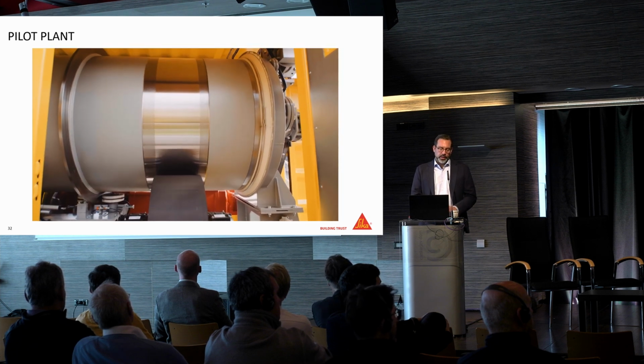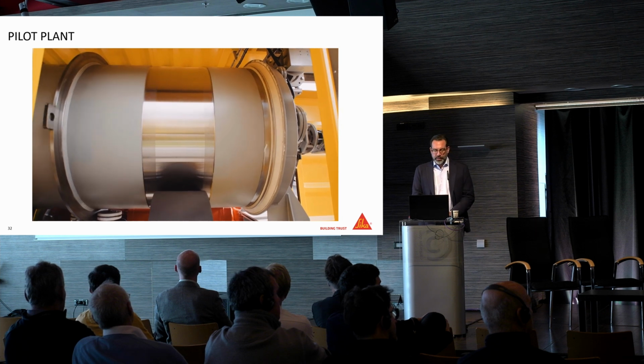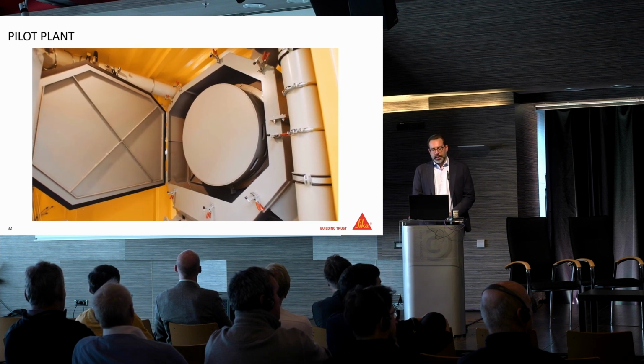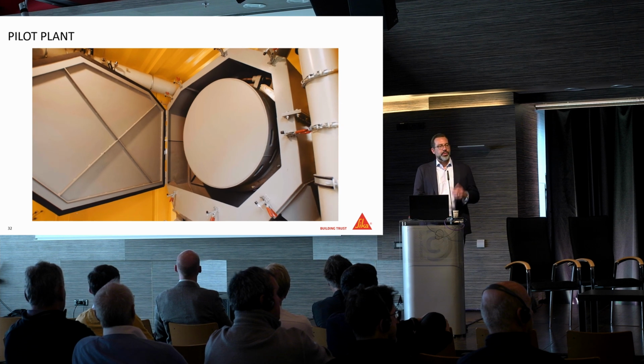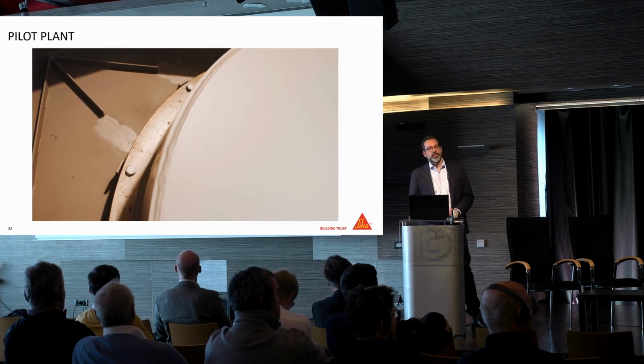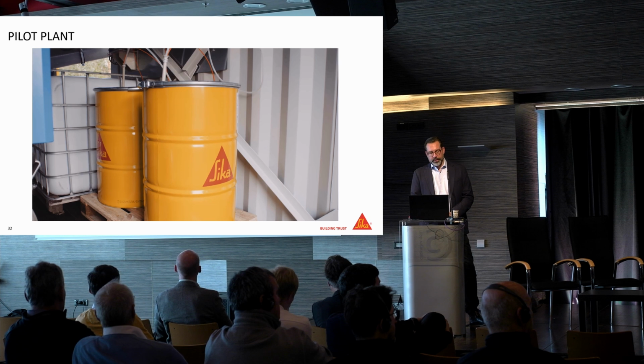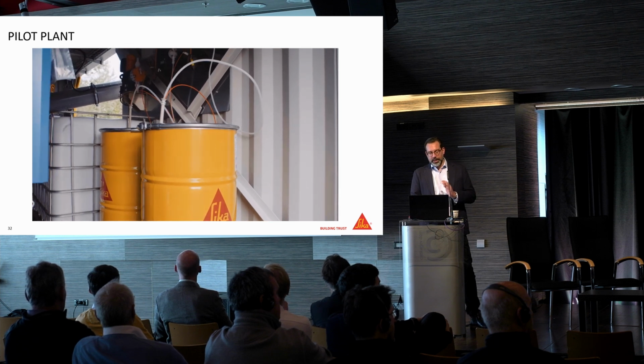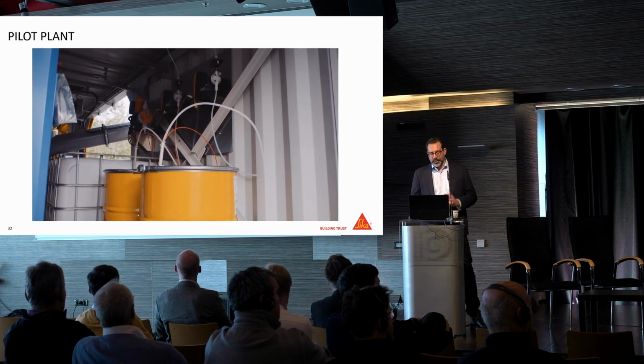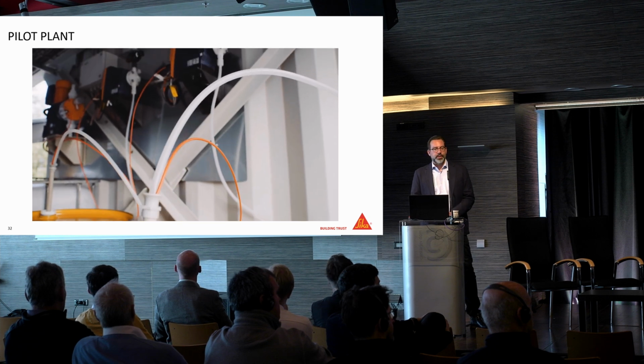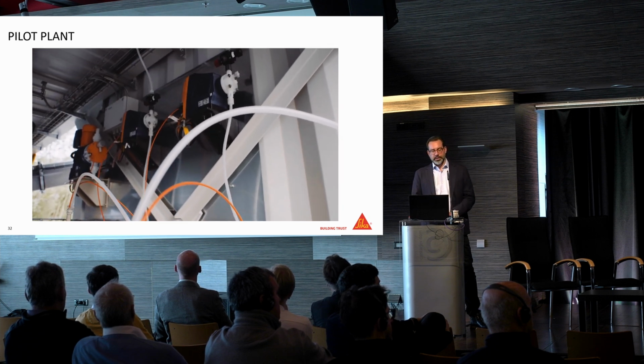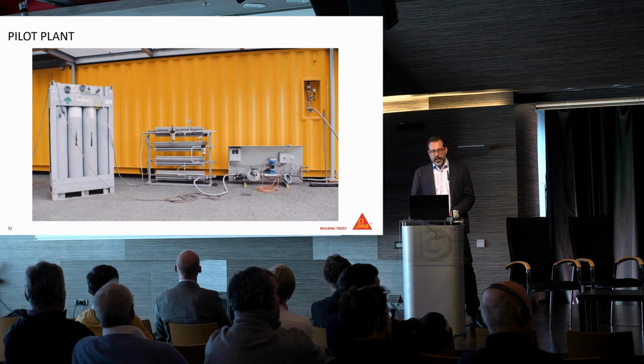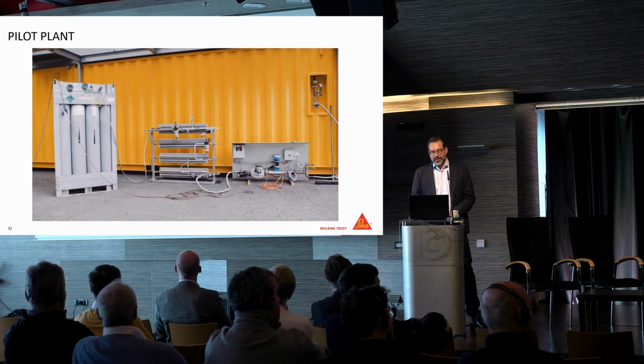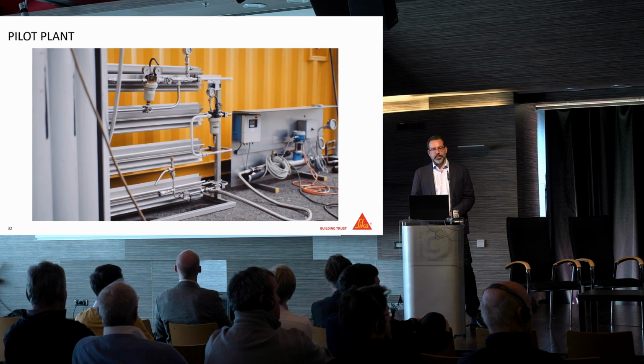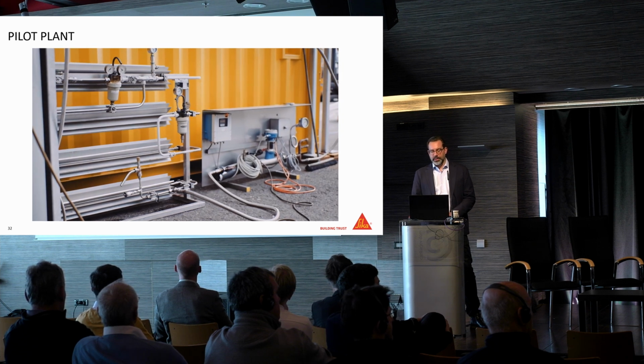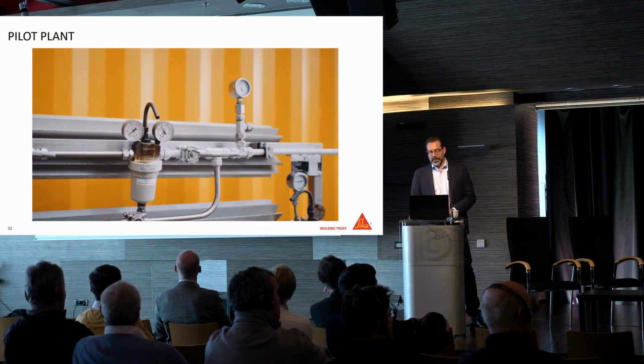At the end of the ball mill, the coarse material falls out, and the finer particles are blown out and taken out with the process air. Of course, we as admixture producer tried several process aids to improve the process, and this is the CO2 that we also supplied to that process, so that it reacts immediately with the powder.